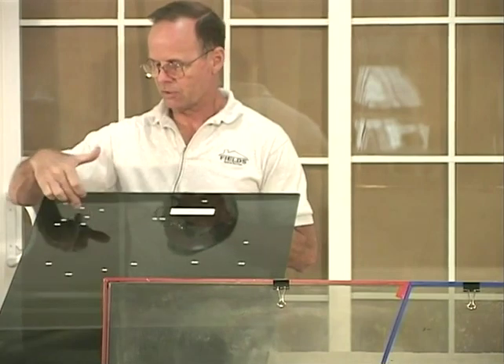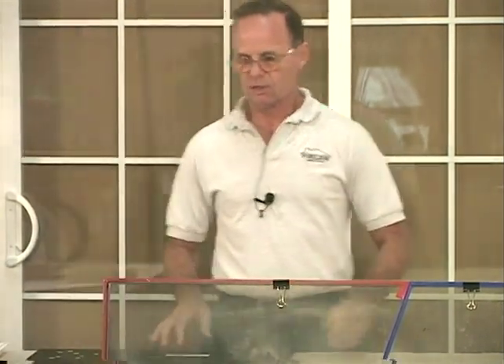And I actually took microscopic images of what tin etch haze looks like, and what water spots look like, and what corrosion looks like. None of them look alike. They're completely different. So when someone says that tin etch haze is corrosion, that the HF just exposed the corrosion, it doesn't look anything like corrosion. Tin etch haze looks completely different. And corrosion actually eats the surface of the glass. It actually cracks the glass into little pieces. Like I say, we'll see the images, and you'll see the difference. There's a major difference between them. Okay? Are there any questions on this?